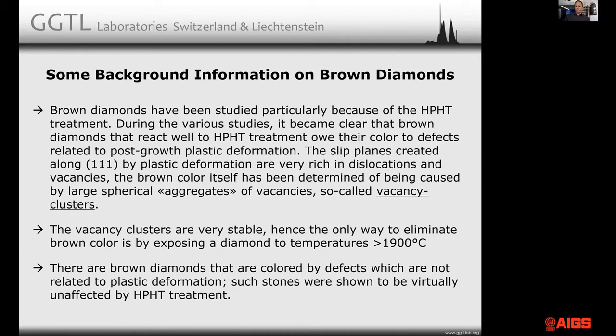It's not a simple vacancy. Vacancy, just to explain briefly, if I talk of vacancy, I talk of the carbon vacancy. So it's a carbon atom not in its spot. It's kicked out of the lattice, puts itself in an interstitial position, so in between the atoms. And the site of the carbon itself stays empty. This empty site is called a vacancy. Now the brown color is not caused by a simple vacancy, but by a very complex, large spherical aggregate of vacancies. They call it vacancy clusters.